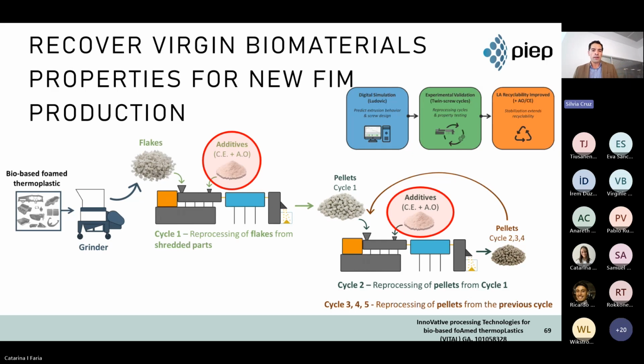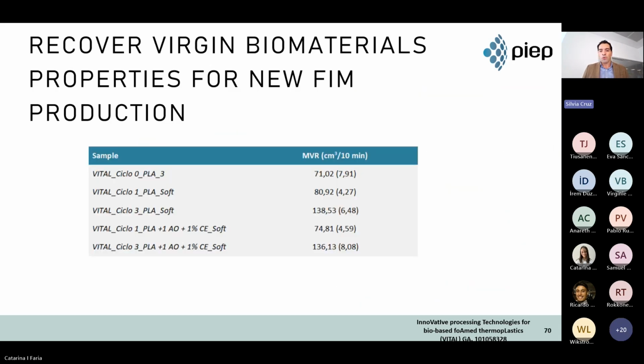Joanna mentioned chain extenders usually are used to avoid the break of the molecular chains of the polymers. So we have some chain extenders, and we also have some antioxidant additives. And the idea was to try to avoid the degradation that was observed during the reprocessing. So again, we run, I will not bother you with more Ludovic graphics, but we run again some simulations.